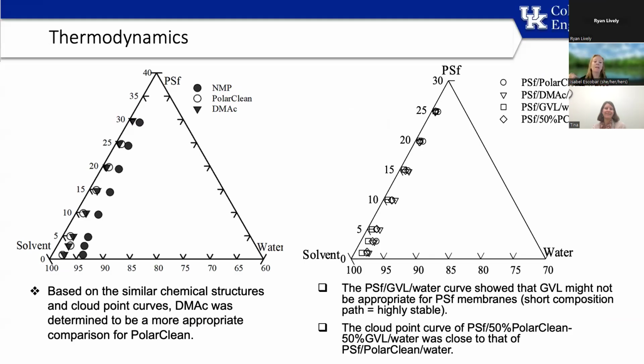We would have to use a lot of water. And as you can see here, the percentage of water that we're adding is the highest. And we would still have issues in actually getting to form the membrane, to getting the GVL to leave the dope solution. So we determined that once we mixed Polar Clean and GVL, we actually were able to make membranes, and we had cloud points. And again, we had very similar operation as when we had just pure DMAC.